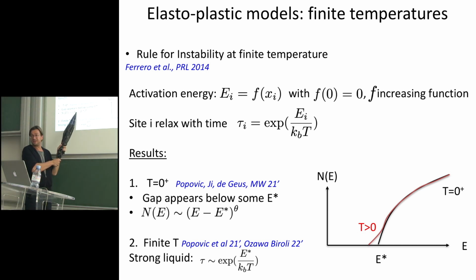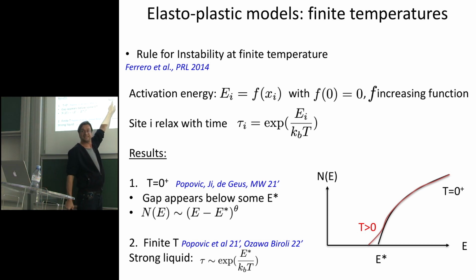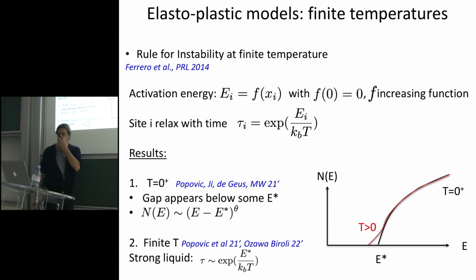If you look at very low temperature, and you plot the density of excitation energy, it's really the same quantity I was extracting in the molecular dynamics simulation, as a function of E. When the temperature vanishes, this displays a gap and a power law just the same as before, with the exponent theta. So let me try to give you an intuition for that.